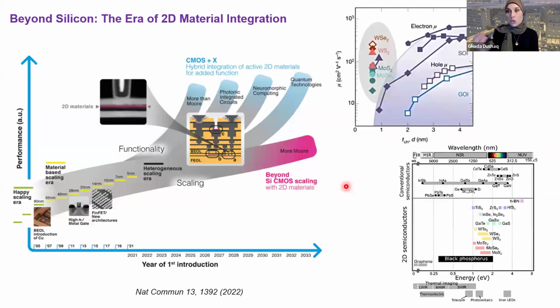And this has also been implemented in electronics, because we could see that, as time goes on and scaling goes more than Moore's, it requires the channel to be smaller and smaller, and you want more and more transistors on the same wafer. And that's when you are talking about 2 to 3 nanometer length of the channel. So we are talking about fundamental limits of the material's intrinsic properties, where we could see that for silicon in this 2 to 3 nanometer range, the mobility intrinsically degrades.